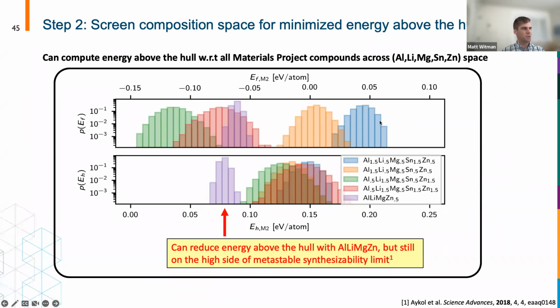We can predict across all these different formation enthalpies. But of course, that's not what really matters for synthesizability. What matters is the energy above the hull with respect to all the other possible compounds that exist in this elemental space. And the fact that all these materials are about 0.1 eV per atom above the hull suggests why experiments weren't able to make, or only saw very faint signatures of, this FCC alloy. One solution could be to get rid of tin, because that gets rid of the possibility of forming this strong magnesium-tin intermetallic compound. But even still, you're going to be pretty far above the hull here. So it's unlikely that you're going to be able to make a pure FCC alloy in this phase space.